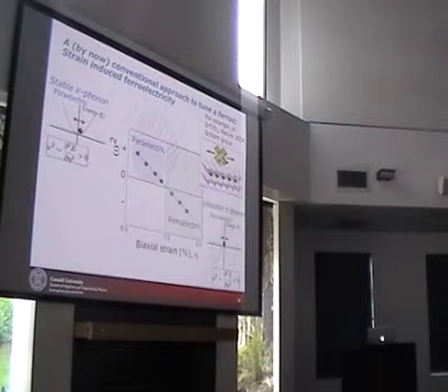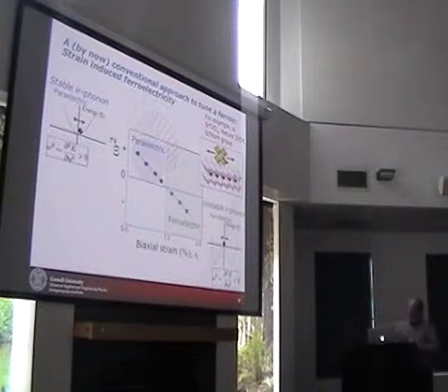We've shown, and people have shown experimentally and theoretically, that we can apply large strains to materials. So you can imagine growing something that is paraelectric, like strontium titanate, on various substrates, applying large in-plane strains by matching up the lattice constants, and driving the system that is nominally paraelectric into a ferroelectric state. So strain controls the onset of this paraelectric to ferroelectric transition.